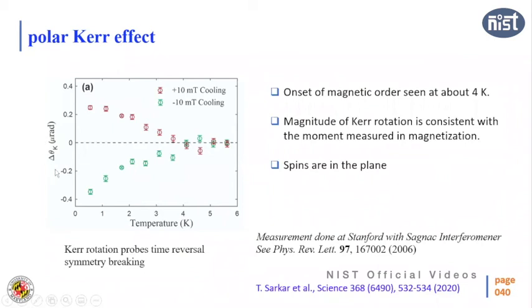Now, if there is no magnetization, what would happen? This delta theta K should be 0. Now, we see some kind of finite value, and it also changes sign with changing direction of the field. And this also vanishes around 4 Kelvin, which is the temperature where the magnetization loop vanishes, and also the magnetization vanishes. So all this suggests that there is definitely ferromagnetism, and it vanishes around 4 Kelvin.